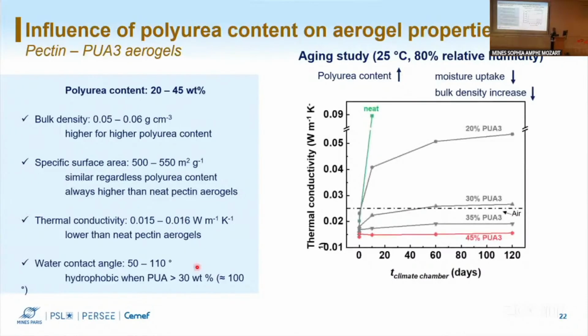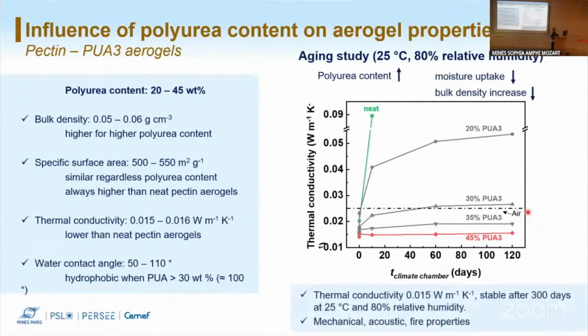For the thermal conductivity, we can see that when we have 35% polyurea in our material, we still have superinsulating properties after 120 days, but only for 45% of polyurea was complete stability reached. For these materials, the thermal conductivity was 0.015 watt per meter Kelvin, and we have an extended study and see that it's stable for almost 300 days. And since they were the most promising materials, we also tested mechanical, acoustic, and fire properties. Very first results that I don't have time to discuss in the presentation, but they seemed very interesting and promising.